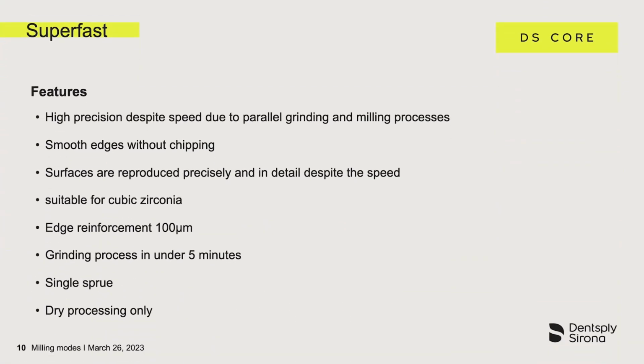Here we are at a very high precision rate, despite the speed, due to the parallel grinding and milling process. We will still get smooth edges without chipping, and the surfaces are rendered precisely and in great detail despite the speed. It is exclusively for zirconia and requires an edge enhancement of 100 microns. Without setting the 100 microns edge reinforcement, milling in superfast mode is not possible. The milling process takes less than 5 minutes. We have a single connector and we can use it exclusively in the dry process.